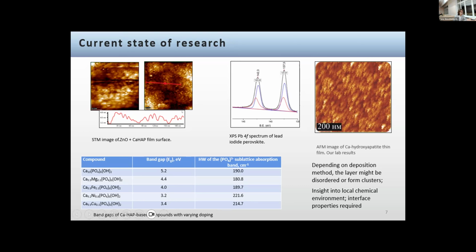And on the left, you can see quite an interesting result. This is a scanning tunneling microscopy picture of zinc oxide mixed with the calcium hydroxyapatite and deposited via magnetron deposition as a thin film. Now, why zinc oxide? It is because if we return to the basic layered structure of the solar cell, zinc oxide is often suggested to be used as an electron transport layer in the solar cell, right? And it's actually adjacent to the perovskite working layer. So this is one of the ways this encapsulation might happen.